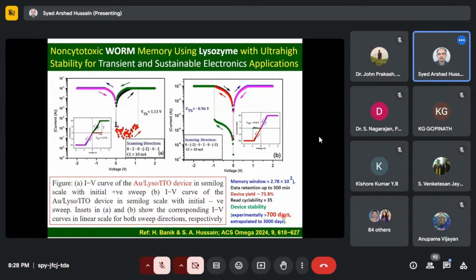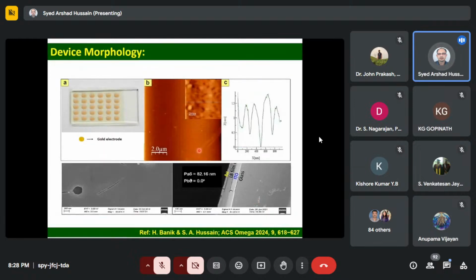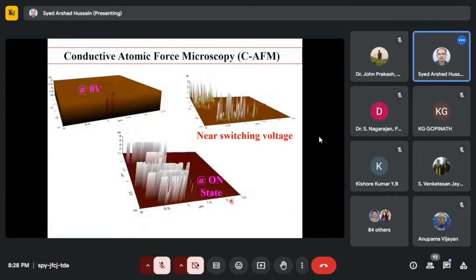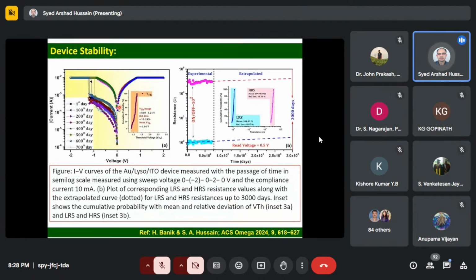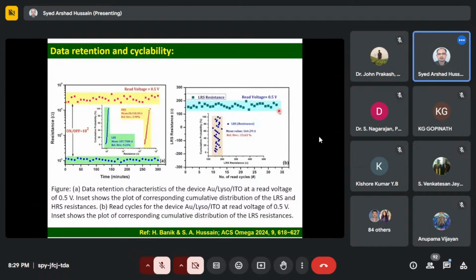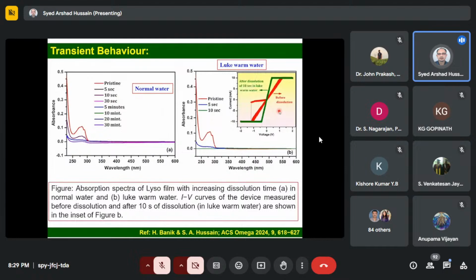So this is the device cross-sectional image. This is the stability we have studied. You can see that it's almost reproducible IV curves even after 700 days. Then we extrapolate using MATLAB software, and we have seen that even after 3,000 days, the gap between two resistance states is good enough to read or to distinguish these two resistance states. That means stored information can be distinguished easily even after 3000 days, which is very good with respect to practical applications. Then we analyze data retention, cyclability, etc., and transient behavior.